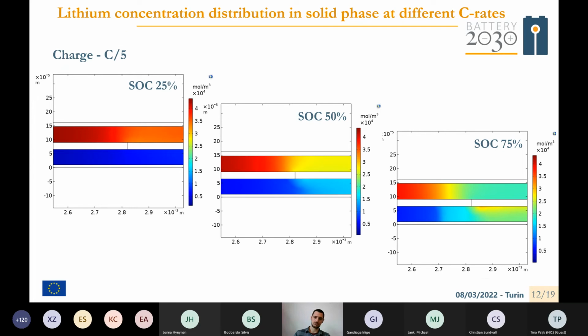I think we have a set of slides from now on that are basically similar to each other, but I will report this plot because you can see that the concentration gradients and abnormal distribution of lithium in the solid phase become more and more important and evident at increasing C rate.